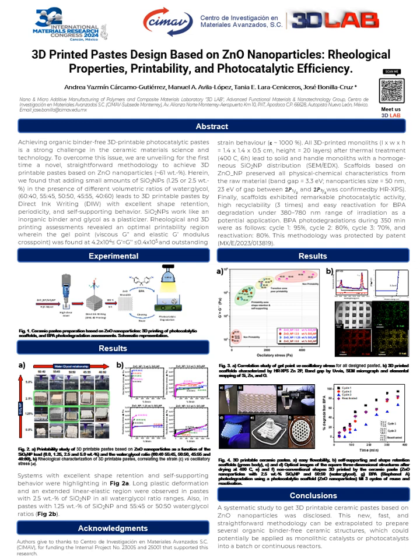The methodology was: we have zinc oxide nanoparticles and silicon oxide nanoparticles. We add water and glycol, we mix, and by direct ink writing, we make the monolith, which subsequently undergoes a heat treatment of 400 degrees Celsius for 6 hours. Finally, it is applied for photodegradation of bisphenol A.